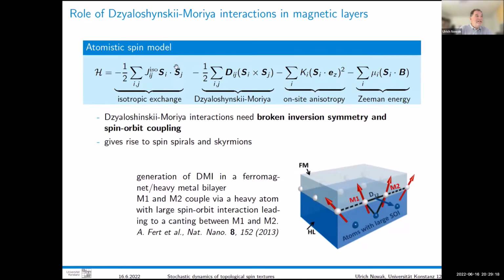In the easiest case, that could be a Heisenberg model, so spins want to be aligned if this is a ferromagnetic interaction. And then you can have more interactions or energies, let's say a Zeeman contribution, a coupling of the spins to a field, some anisotropy, let's say a uniaxial anisotropy in some direction. And for skyrmions, you normally also need a Dzyaloshinskii-Moriya interaction. There are different ways how you can produce skyrmions, but that is, let's say, the most effective way.